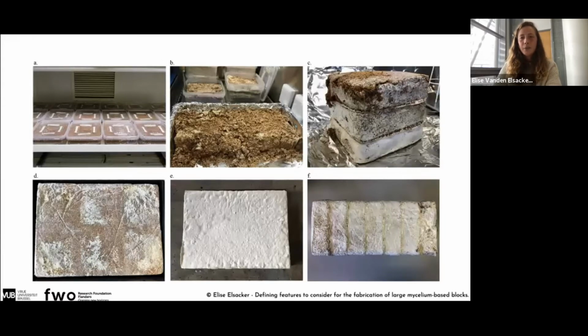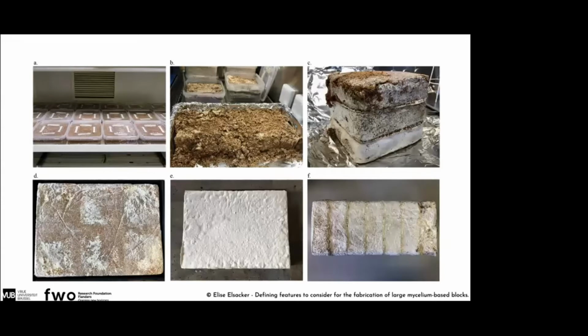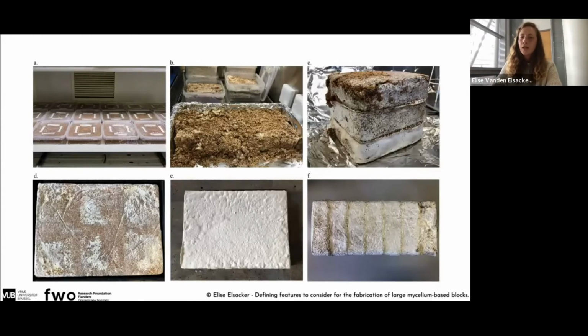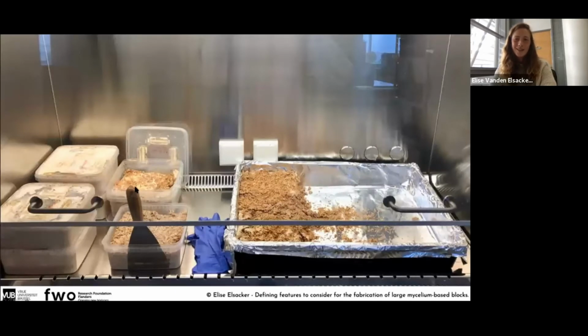Before the fabrication of the large mycelium blocks, I did some experimental work to select the most appropriate growth protocol, because it could be approached in different ways, and I knew that mycelium materials wouldn't really grow through the substrate if the samples were much larger than about 10 to 15 centimeters. So I tried different ways. First by growing everything in boxes in advance, and then placing those blocks horizontally next to each other in a larger panel. I also tried to stack compressed blocks vertically, and also stacked pre-grown but not compressed blocks. I will quickly go through all those experiments.